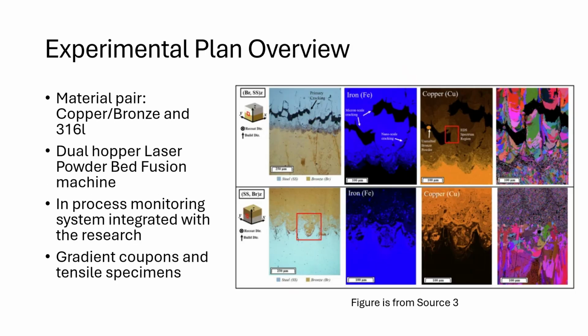As I mentioned earlier, I'll focus on the copper and 316 combination for its balance of conductivity and strength and its interesting applications for both thermal and electrical conductivity. I will use the Additive Suite tool that ANSYS offers, where I will characterize the prints and mechanical properties of my intended coupons in simulation. Then, using a dual hopper commercial laser powder bed fusion system, I'll print gradient transition coupons for several different types of mechanical testing, incorporating in-process monitoring to relate melt pool data to resulting microstructures in the metals.